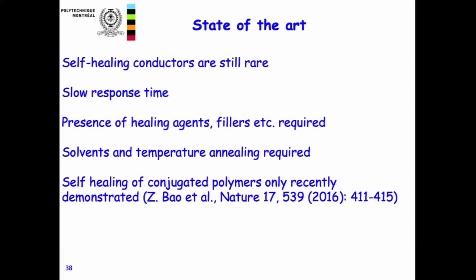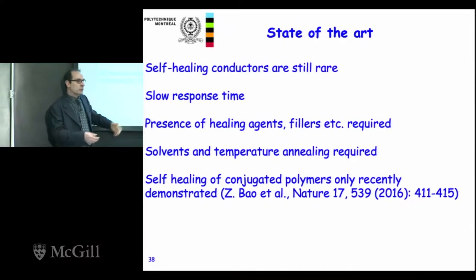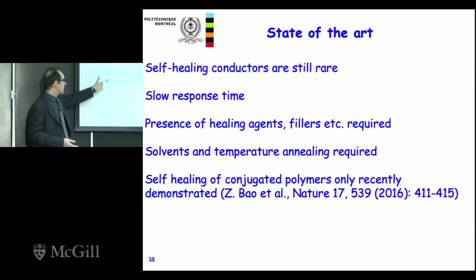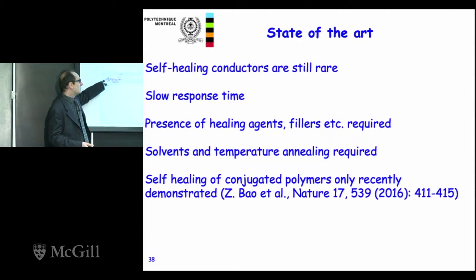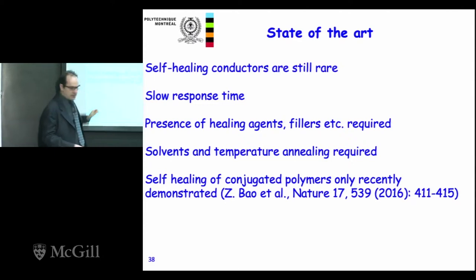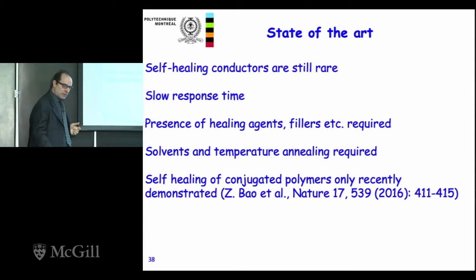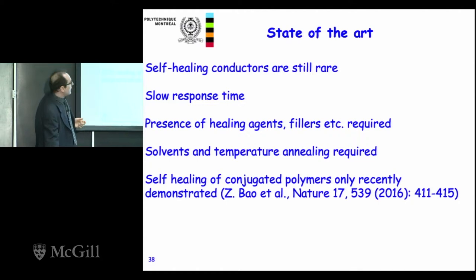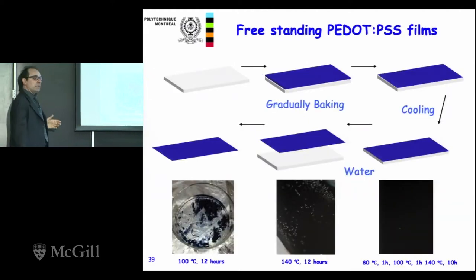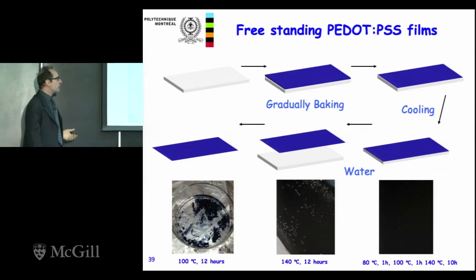Then usually you have to add some healing agents to the material to make it healable. And sometimes you also need to treat them with solvents or bring them to high temperature. And actually, not so long ago, the first organic semiconductors that are healable have been reported. So we showed that the self-standing PEDOT:PSS film can be self-healable.